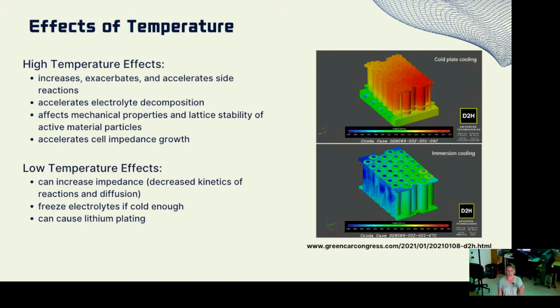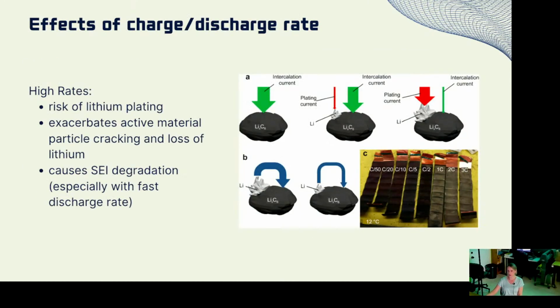And just a little bit on the effects of temperature. Like I mentioned earlier, in the wintertime, there were lines and lines at these charging stations because it was taking forever to charge a battery. And while I could see how someone would get really upset, like, oh, I paid for this car, it said it was going to charge at this rate for fast charge, why isn't it doing that? Well, we talked about lithium plating and dendrite formation. If the battery's really cold, the lithium moves slower through the materials, and it could cause a traffic jam and could cause lithium plating if you charge it too fast. And so those slow charges are actually protecting a lot of people from any kind of harm and danger. But it is a challenge to maintain that temperature so that you can have safe charging and safe operation and keep that temperature uniform.